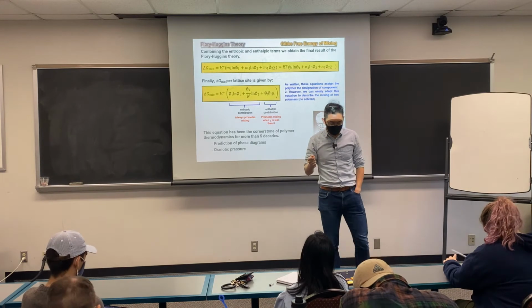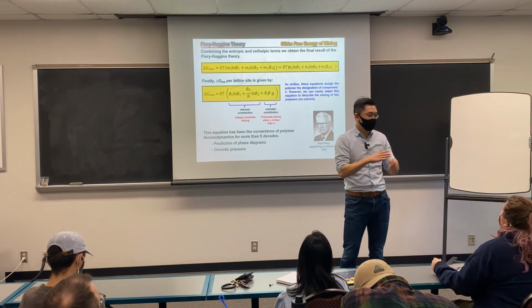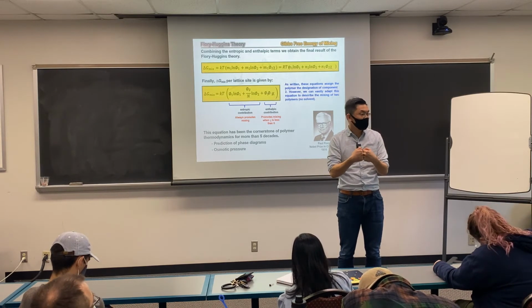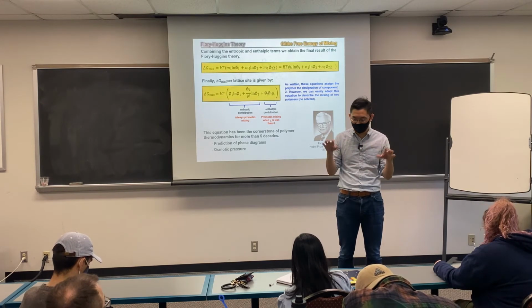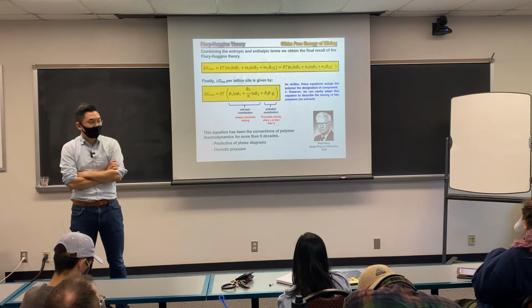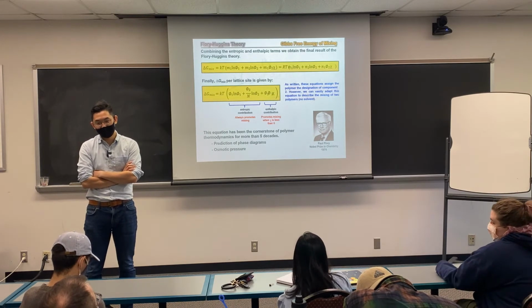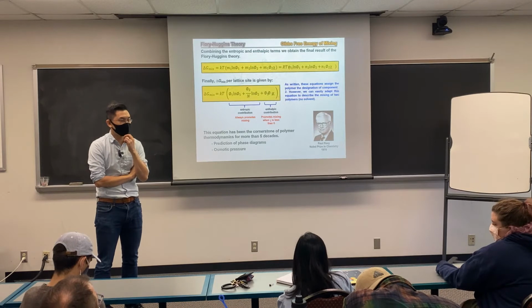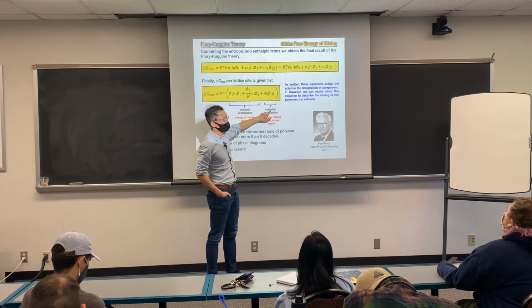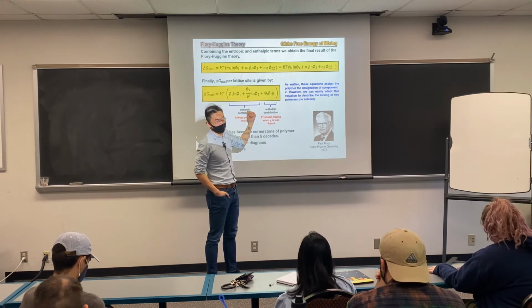So let's think about a few scenarios. What if chi is bigger than 0? Chi is a positive value. That means there are repulsive interactions between your polymer and solvents. The polymer prefers to assemble, the components prefer to just stick with themselves. So in this case, whether the polymer can be dissolved depends on specific scenarios. Because when chi is positive, this phi 1 phi 2 chi term is going to be positive. So the interaction term does not favor mixing, but it needs to have a battle with entropy and see who wins out. So it's unknown.